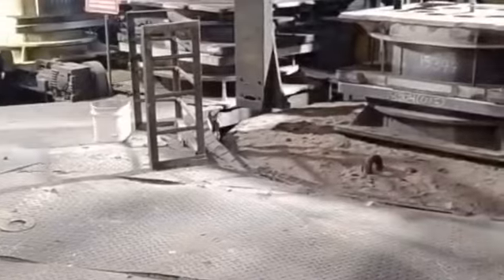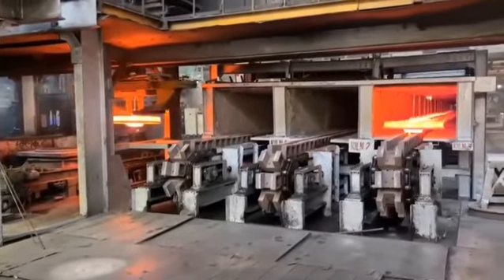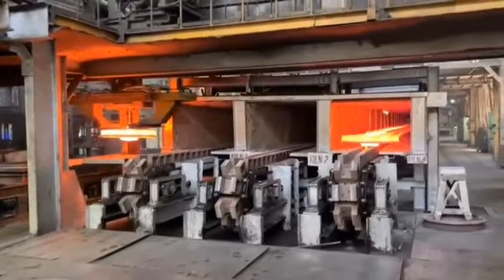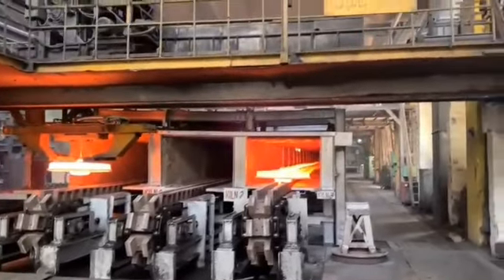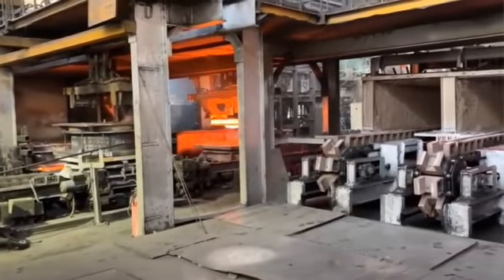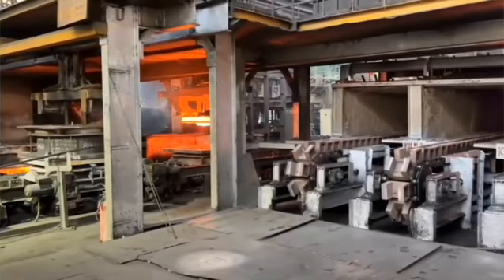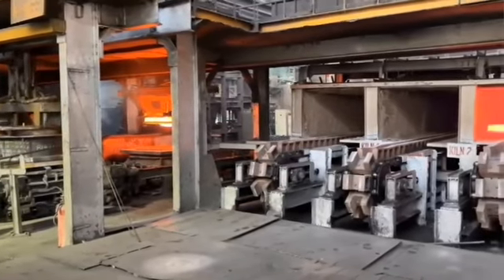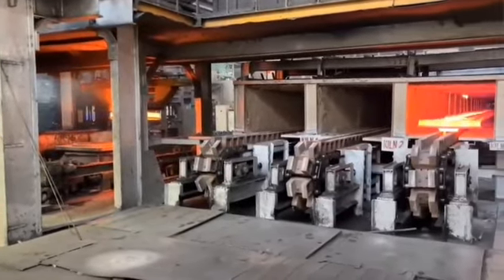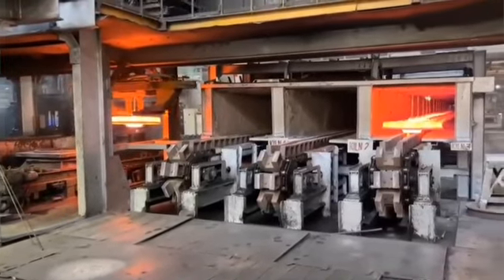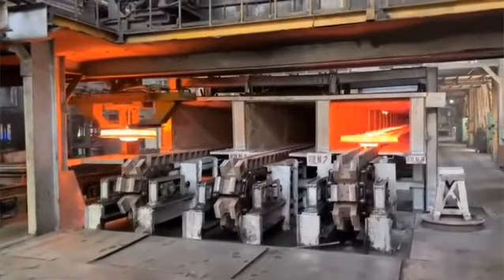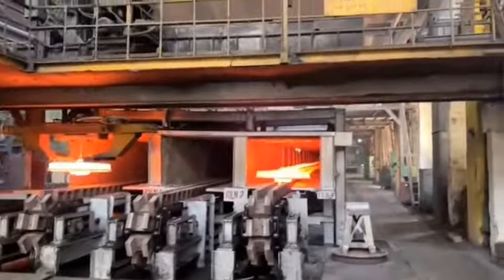Once the metal is poured, paddy husk is added to the assembly through riser holes to prevent sudden drop in temperature of molten metal, which otherwise would produce cracks/flaws in the surface of wheels. The cope is clamped and lifted gently. Sometimes, wheel sticks to the cope, so the crane moves up and down over the drag controlled by the operator. The wheel is placed in hot wheel kiln, where it is subjected to controlled air cooling. The cycle time is 32 minutes.